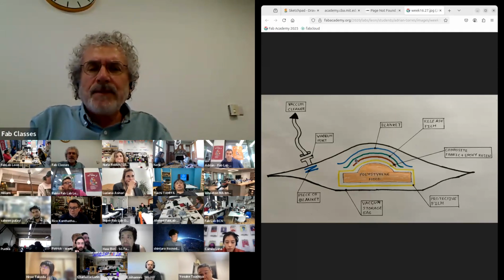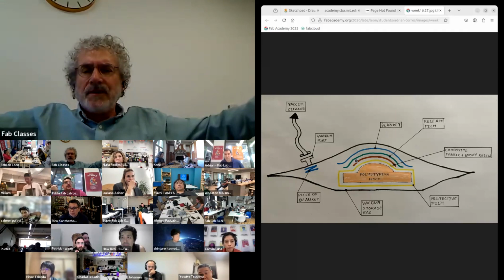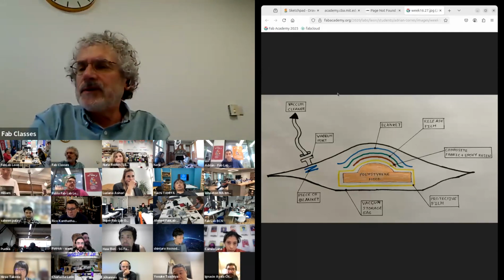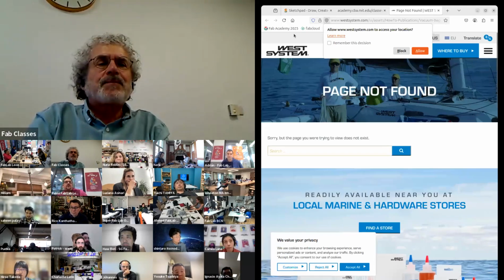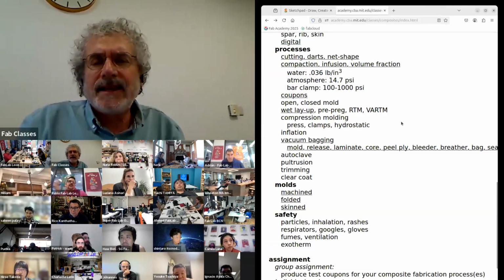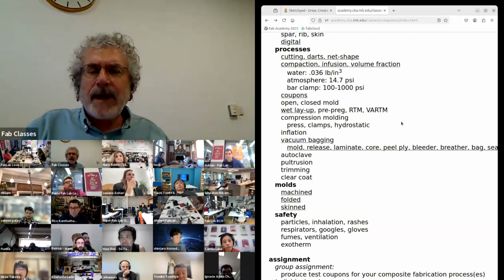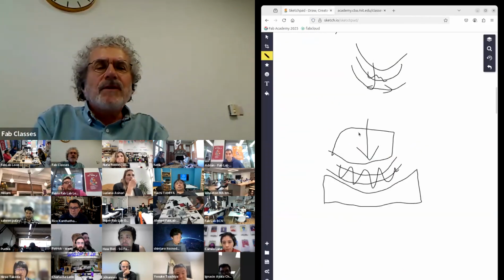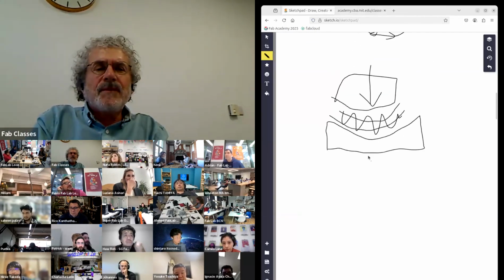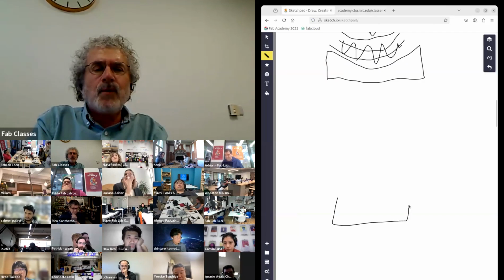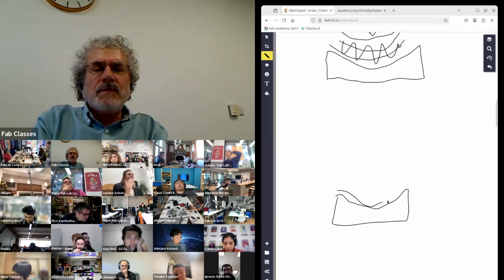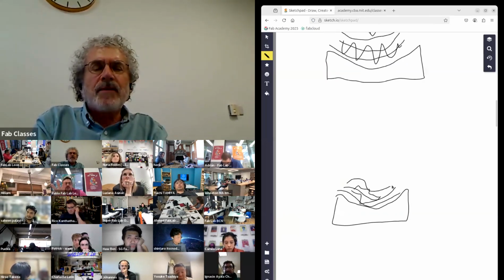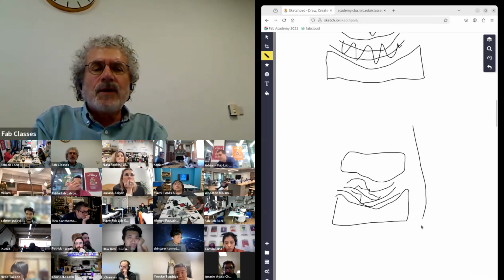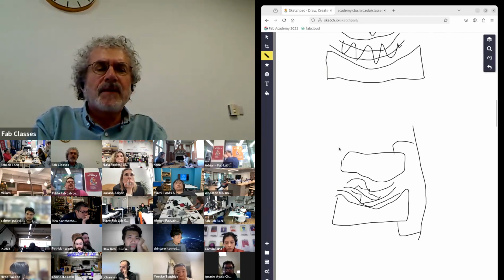And so what's good about vacuum bagging is it works over any size area. The force you need doesn't vary because you're not producing the force, you're just generating the vacuum. What's bad about vacuum bagging is it's a fair amount of work to make the vacuum bag and do all of those steps. And so generally what I prefer is, let me just explain that same image again. So you make one side of the mold, lay up your fabric, spread some resin, lay up another ply of fabric, spread some resin, lay up however many plies. You bring in the other side of the mold, then we're going to clamp the whole thing.